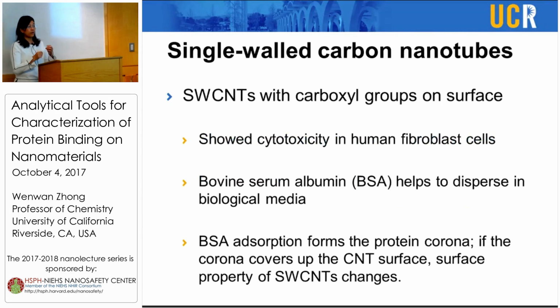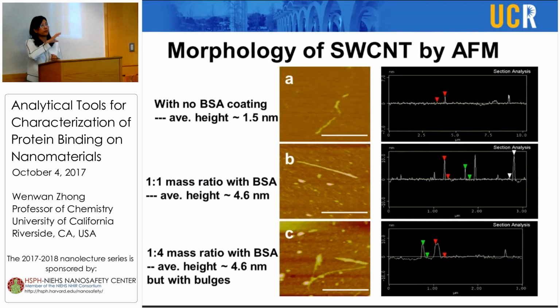So we want to see how this protein absorption will prevent formation of protein corona inside cells, so then could potentially provide some protective effect. So what we did is we prepared some carbon nanotube coated by BSA, but using different mass ratios. For example, 1 microgram of this carbon nanotube coated by 1 microgram of BSA, or 1 microgram of carbon nanotube coated by 4 microgram of BSA. So with a larger mass ratio, AFM shows that the coating on the carbon nanotube is thicker, right? And then this thicker coating will affect the